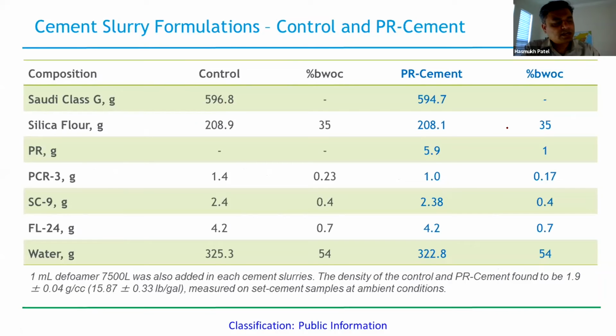So let me show you some of the experimental results that we have. As you can see, for the cement slurry formulation, we prepared the control and the cement with PR, which is polyrotaxane. These are the components we use: the cement, silica, and polyrotaxane. We use three different additives, mainly for rheology control, for example, to ensure there is no fluid loss or water separation from the cement matrix. We are using about 1% of polyrotaxane in the cement. All other components are the same in both formulations.